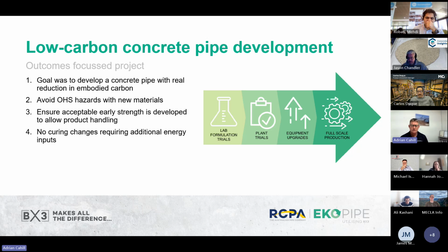As it turns out, when you do remove Portland cement, you have to provide some level of control around curing, just for predictability as much as anything else. So pretty typical process. In 2015, 2016, we went back to the lab, started working on a range of different options. We got to the point after a couple of years where we found a solution that seemed to work quite well for a dry cast, vertical cast concrete pipe.